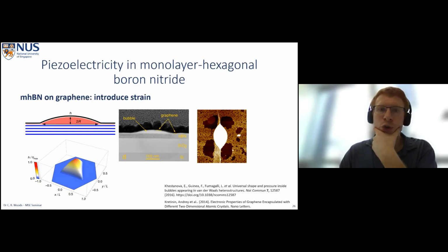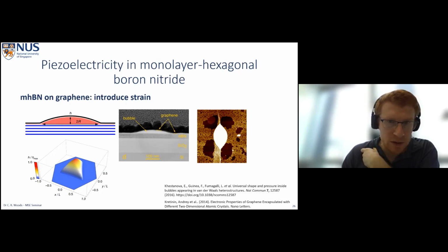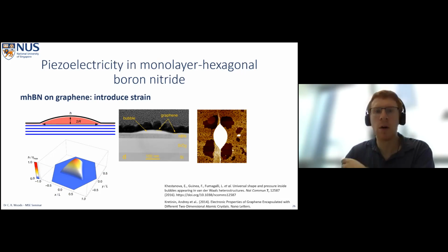So in short, you might see something, but I would expect that if you put the monolayer boron nitride onto a substrate of graphene, that's where the effect will be more strongly observed.